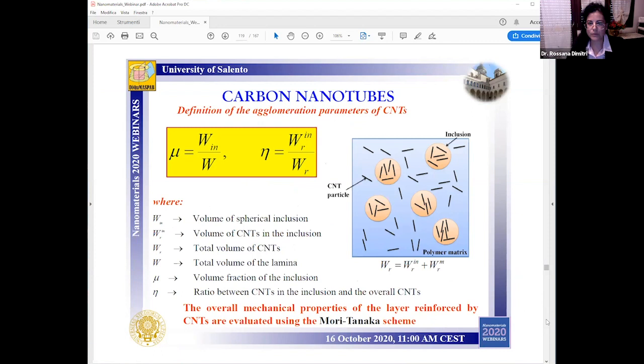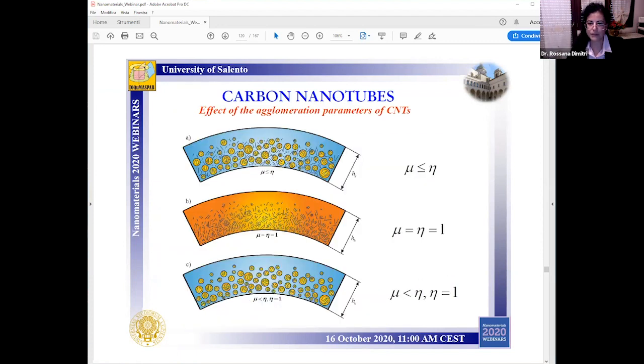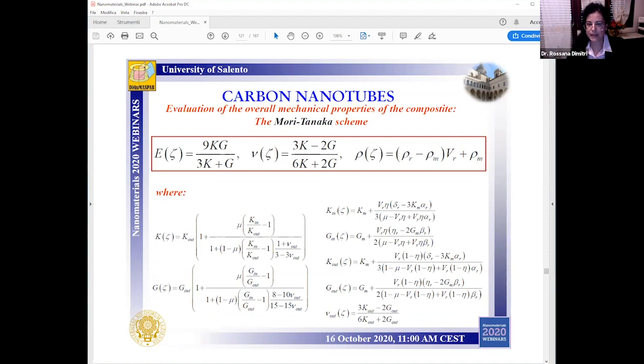So a two-parameter agglomeration model is defined by means of these two quantities, eta and mu, where the first parameter is the volume fraction of the inclusion, I mean the ratio between the volume of the spherical inclusion and the total volume of the lamina. And the second one, eta, is the ratio between carbon nanotubes in the inclusion and the overall carbon nanotubes. So depending on the different relation between these two parameters, we can obtain different agglomerations of carbon nanotubes within the material. And the overall mechanical properties of the composite can be determined in a homogenized form according to the Mori-Tanaka scheme.